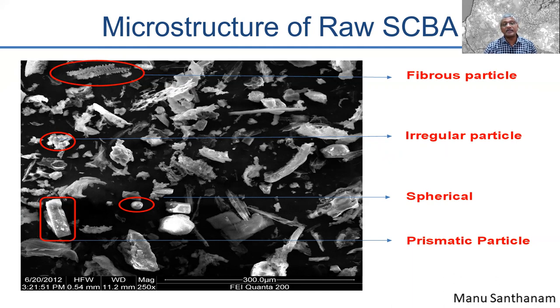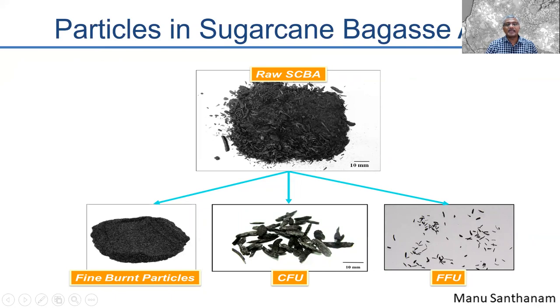And this shape, especially prismatic, results from crystalline materials that are present in the system. The fibrous particles, you can try and attribute to carbon-based materials, but you still need to confirm it. And that's what we did with energy dispersive spectroscopy. The irregular particles are the ones we are interested in, because those are the silica particles, again established through energy dispersive spectroscopy. So essentially, your raw bagasse ash is composed of this fine powder, which is basically the fine burned silica particles. You have the coarse fibrous particles, which are of 10 millimeter size, and you have the fine fibrous particles, which are of 1 millimeter size. So both these particles need to be removed from your system to really get a better performance from your bagasse ash. So how do you remove them is the question.